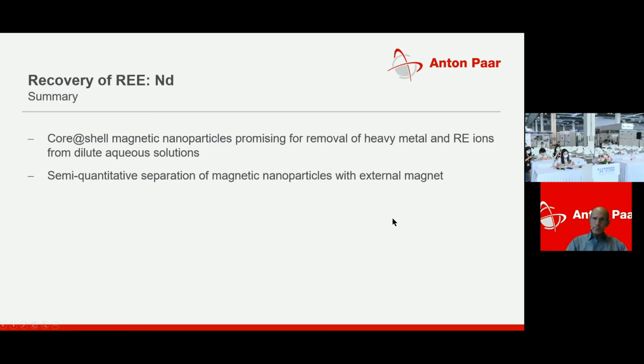However, we observed that the intended removal of magnetic nanoparticles by an external magnet is not quantitative due to the fraction of small-sized particles, which require the additional application of a centrifuge or even filtration with a 20 nanometer filter, because remaining nanoparticles in solution with adsorbed rare earth ions may change or falsify the conclusion on the removal efficiency for these ions, since they contribute to the absorbance of neodymium in UV spectroscopy.